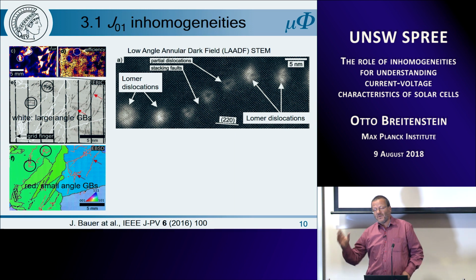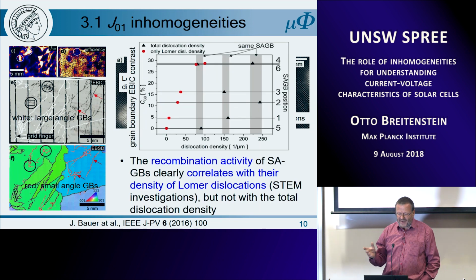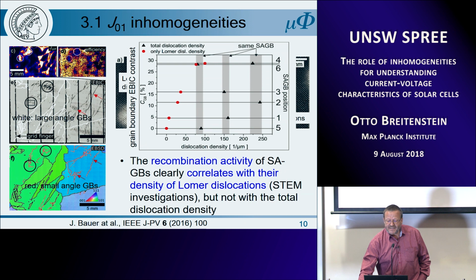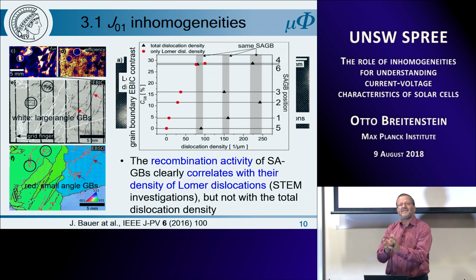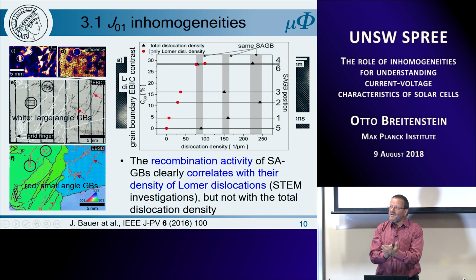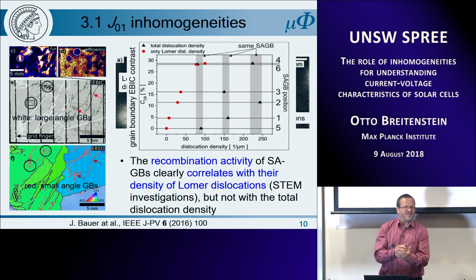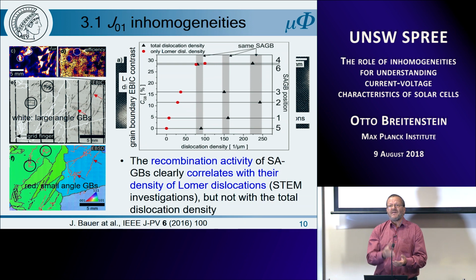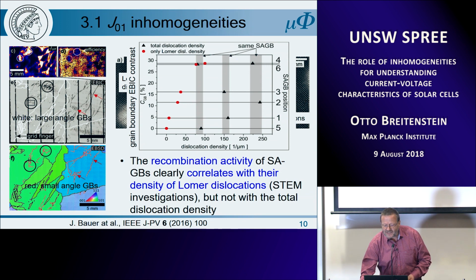And as I told, we have prepared in 6 positions. And then we have made some statistics. So we knew from the EBIC results the contrast in percent. And then we have measured, by evaluating the TEM results, the total dislocation density, irrespective of their type, and the density of only Lomer dislocations. So the red points are if we count only the Lomer dislocations, and these points are if we count the